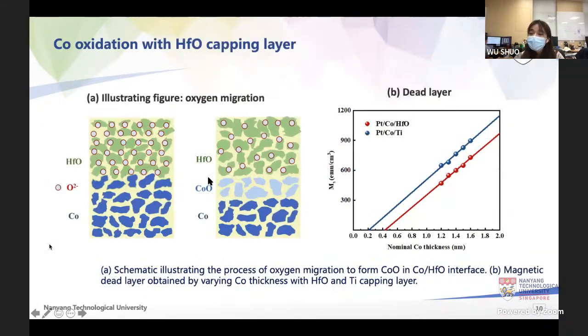Then, to confirm the assumption of cobalt oxidation at the cobalt/HFO interface, we use VSM to measure cobalt films of different thickness and get their Ms. You can see in this figure, the Ms of the Ti capping sample is always higher than the HFO capping layer samples. This indicates the oxidized cobalt results in a reduction of the overall saturation magnetization of the cobalt layer. So there is cobalt oxide forming after the oxygen migration.